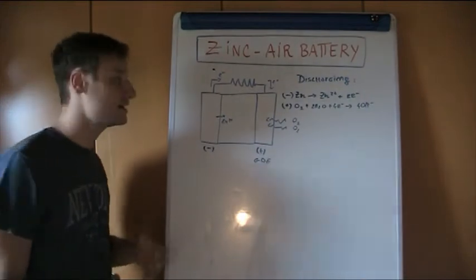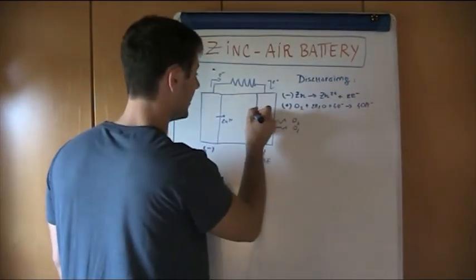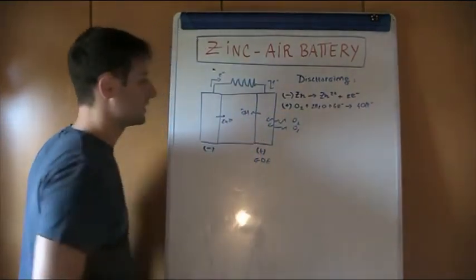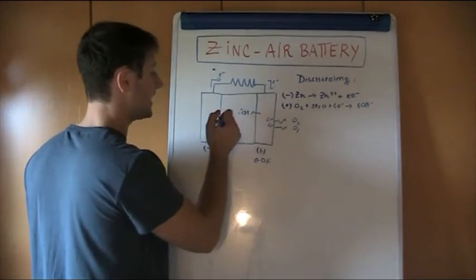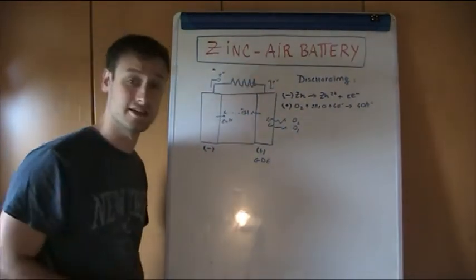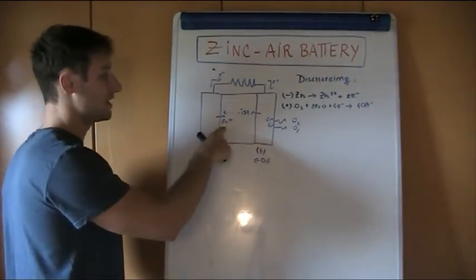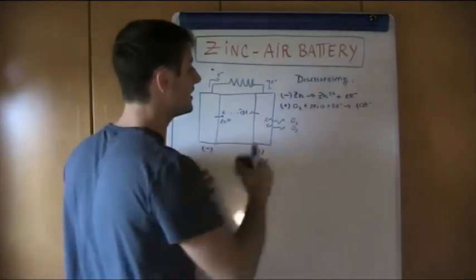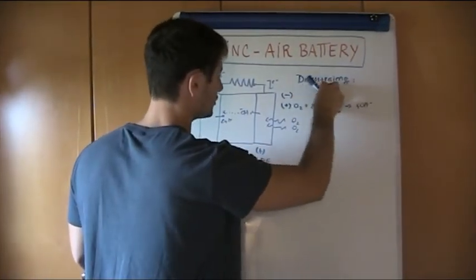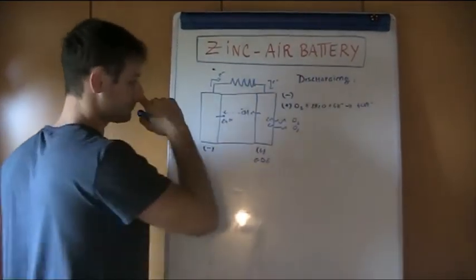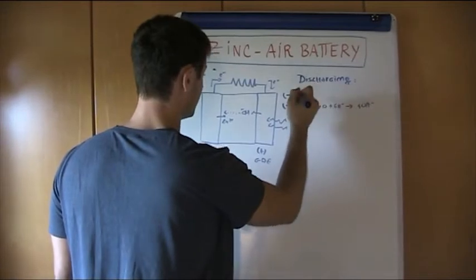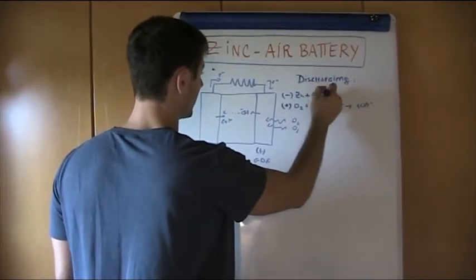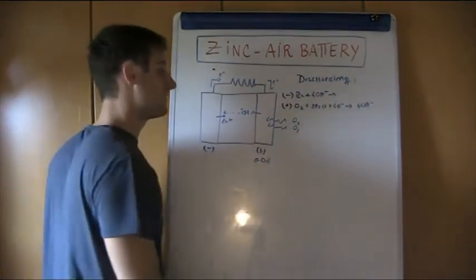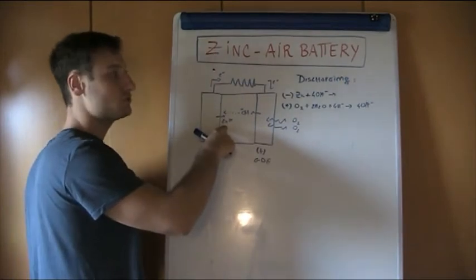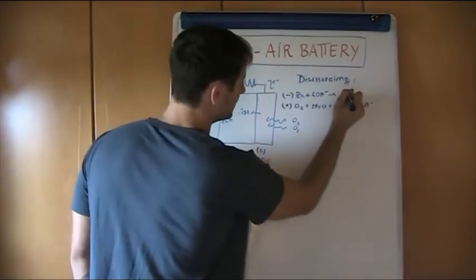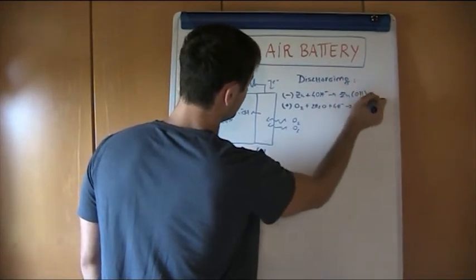To be honest, this product, the generated OH minus, can migrate during the discharging to the surface of the negative electrode and react together with the zinc 2 plus. And so this means that in reality the real discharging semi-reaction is basically this one. We have the zinc reacting with 4 times OH minus, and this leads to zinc 2 plus, but zinc 2 plus in the form of zincate. So the zincate is this species.